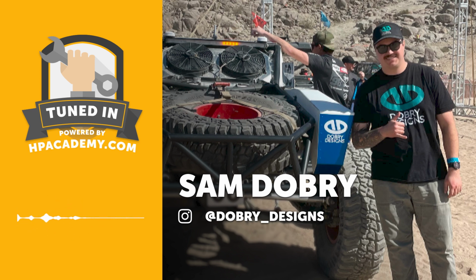The thicker your oil is, the more that oil will want to hold on to those cavitation bubbles. So essentially you're getting those bubbles pass through, and those bubbles caused by cavitation, I'm guessing here, are actually doing damage to the bearing surface. Is that what you're sort of getting at? Not only is it doing damage to the bearing surface when they pop, they're also significantly hotter. So the vapor that's caused in that whole system is thousands of degrees. So you hold on to a ton of temperature when you run a thicker oil.